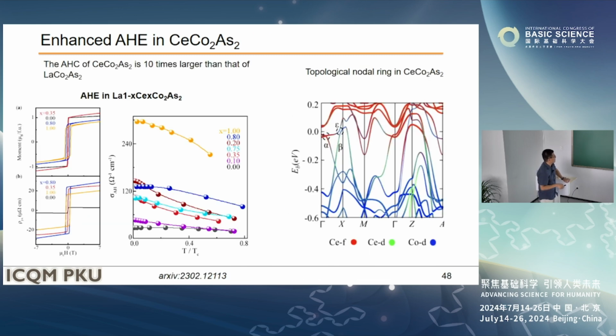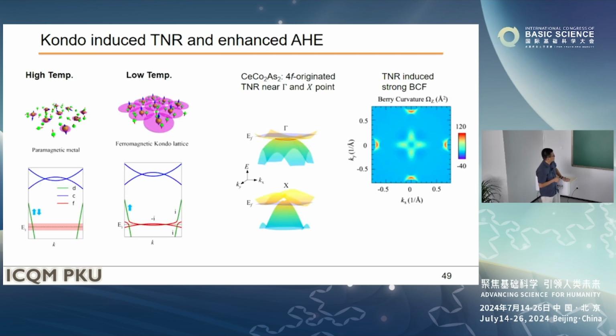So we did some Hall effect measurements. We find the anomalous conductivity is 10 times larger than the lanthanum compound. And our collaborator did some band structure calculations and showed this. We find a topological nodal ring band structure in CeCo2As2. So next, they want to test whether this topological nodal ring is a Kondo effect induced topological nodal ring, meaning it starts from strongly correlated electrons. So what is the picture?